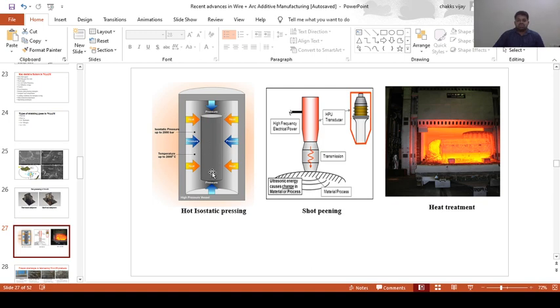In certain circumstances we generally go for hot isostatic pressing, but this is restricted with wire arc, because most of the articles mention that there is no appreciable effect of hot isostatic pressing on wire arc additive components. However, it is more effective with powder-based additive components.